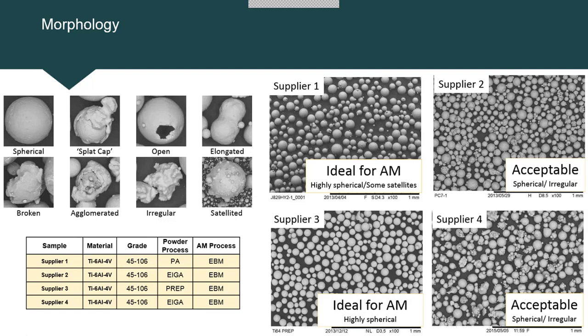When we're looking at morphology, like I mentioned, ideally we want spherical particles. What we want to be avoiding is some of the examples shown in the top left there, things like the splat caps and the elongated and broken agglomerated particles. They're the kind of particles that are going to start to form effectively interlocking. So they're going to reduce our level of packing, and they're going to prevent our ability for the powder to flow and to spread in the dosing unit.